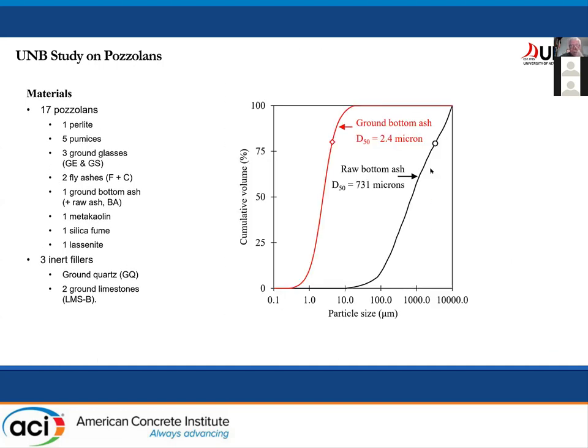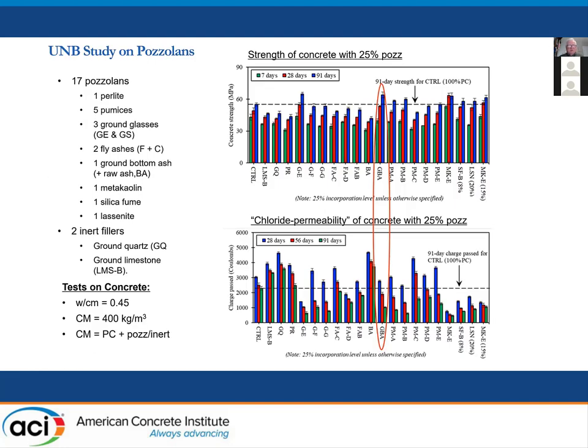And again, Mahipal did some work with the raw bottom ash and grinding it down to fly ash sizes here. And so some of the graphs will show the raw ash versus the ground bottom ash. And so here's strength at 7, 28, and 91 days. That's concrete now, concrete made with the materials. And you can see that it develops increasing strength at 3 ages, and the control is the Portland cement over here on the left-hand side.